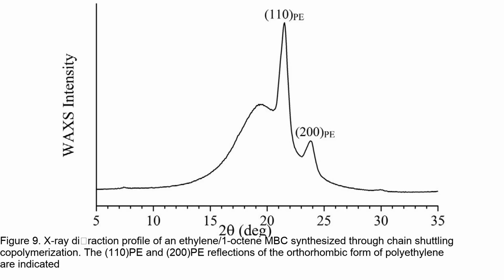Figure 9 in the paper shows the X-ray diffraction profile of an ethylene, 1-octene multiblock copolymer synthesized through chain shuttling copolymerization. The diffraction pattern indicates the presence of the orthorhombic form of polyethylene (PE) crystals, as evidenced by the 110 PE and 200 PE reflections. This confirms the semicrystalline nature of the copolymer.